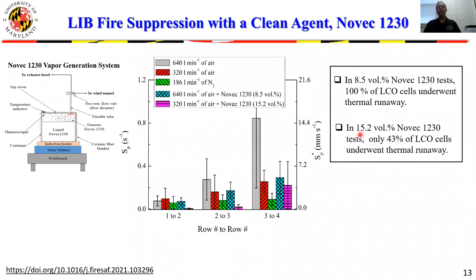What we found from these experiments was that at 8.5%, the application of this suppressant was able to slow down the thermal runaway propagation, but did not stop the combustion, and the propagation always was complete. In fact, we found that some of that agent potentially enhanced combustion in this tunnel. So we observed higher combustion efficiencies when we introduced Novec 1230 than without Novec 1230.